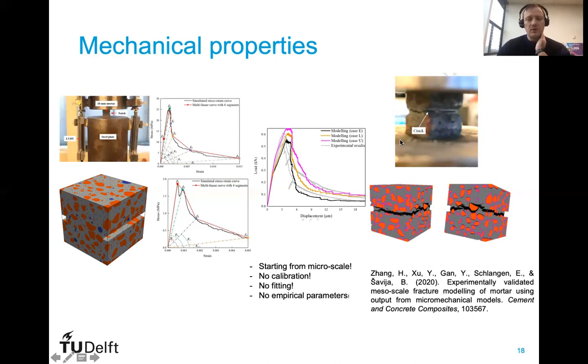What is important to notice is that in this case, we started from the micro scale. So we measured only at the micro scale, and on upscaling, we didn't do any calibration, any fitting, or adding any empirical parameters to get a better match between the experiments and the simulations. So this presents an experimental and numerical framework for multi-scale modeling of mechanical properties of cementitious materials that can be easily repeated for different properties, for different matrices, with different additives, for example, such as nanoparticles, and so on.